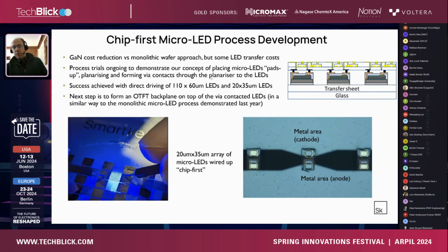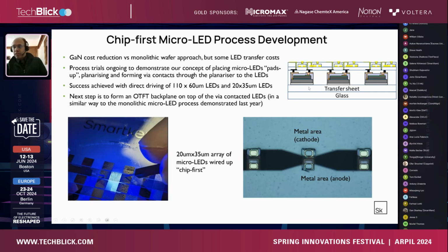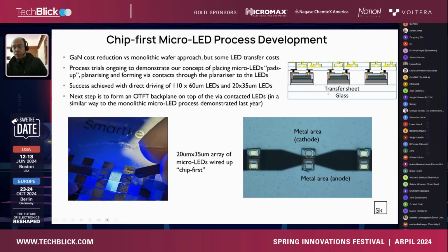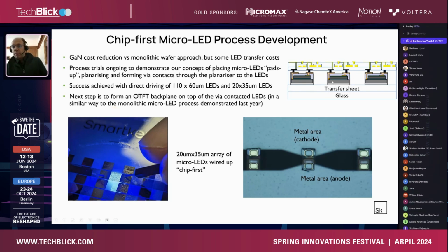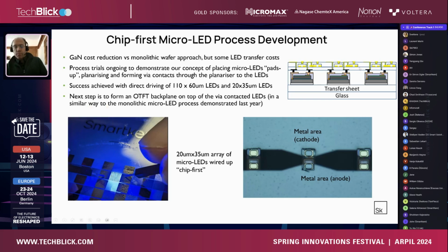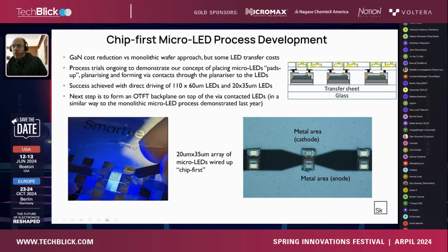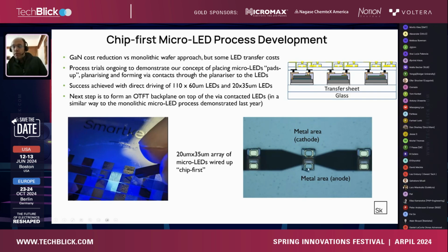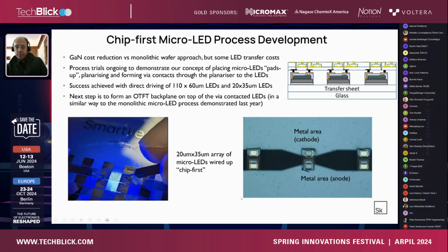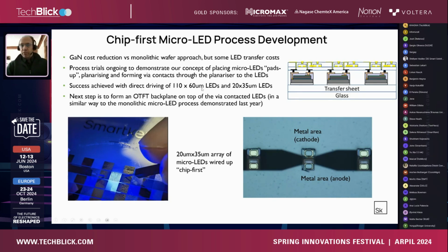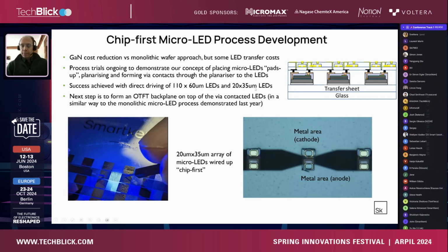So the next development that we're doing is to use a hybrid of the current pick and place process, where you would space out the LEDs from a source wafer onto a transfer sheet, which is an intermediate carrier that can be much larger than the wafer, and therefore use much fewer LEDs per area, and then build the backplane on top. This shows the first experiments to show that we can take spaced-out LEDs and then put down an insulating layer, which we develop ourselves, bias through, and then sputter contacts down onto the anode and cathode, and then light them up to show that we're getting a good electrical contact. We've done this with both 110 by 60 micron LEDs and 20 by 35 micron LEDs.